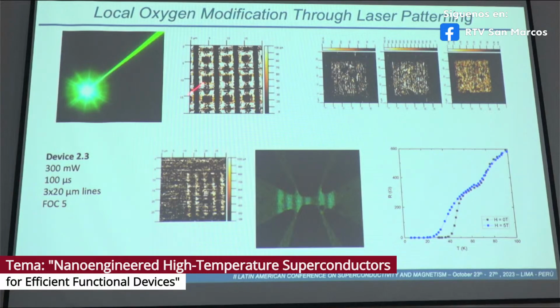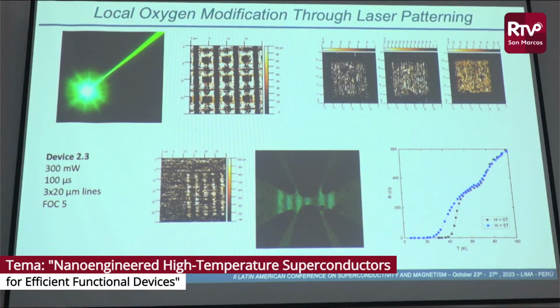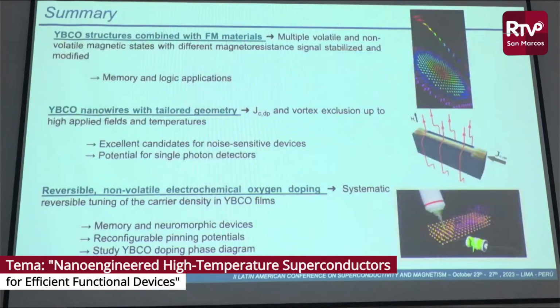And in this case, this is a work that we have started recently to try to modulate the oxygen. Here we see the contrast of one image that has been irradiated with a laser, and with the heat that we generate with the laser, we are able to introduce oxygen vacancies in the system, also modulating the TC by changing the heat.